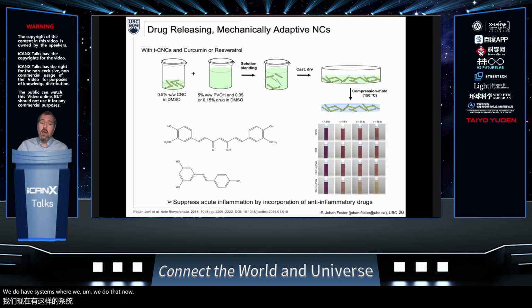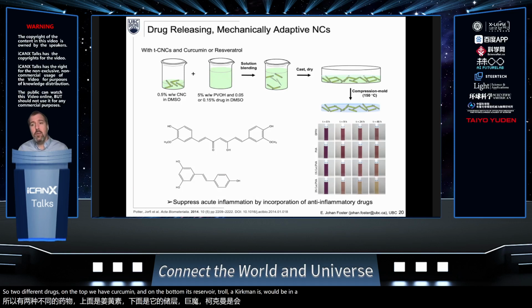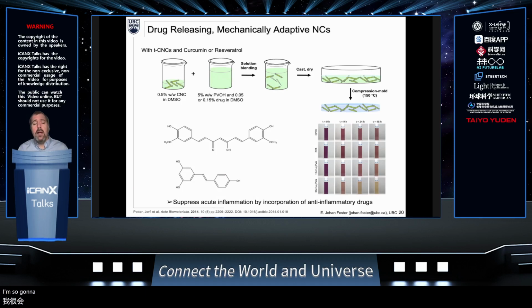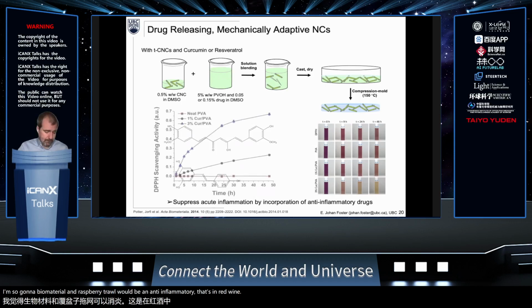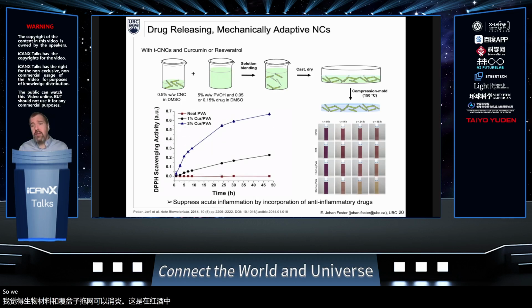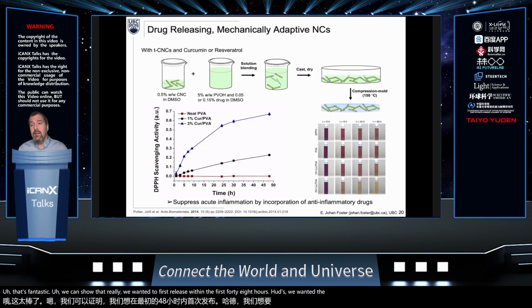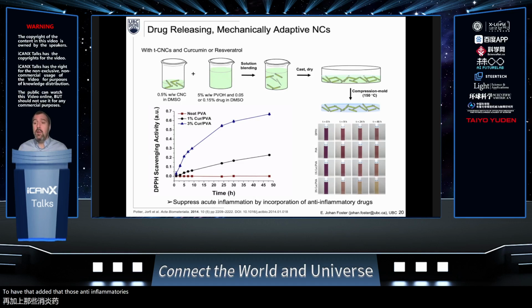Okay, so two different drugs. On the top we have curcumin, and on the bottom it's resveratrol. Curcumin would be in turmeric, so again a biomaterial, and resveratrol would be an anti-inflammatory that's in red wine. Okay. So we can show that we've got release over time. That's fantastic. We can show that really we wanted a burst release within the first 48 hours because we wanted the site of inflammation to have those anti-inflammatories most dramatically.